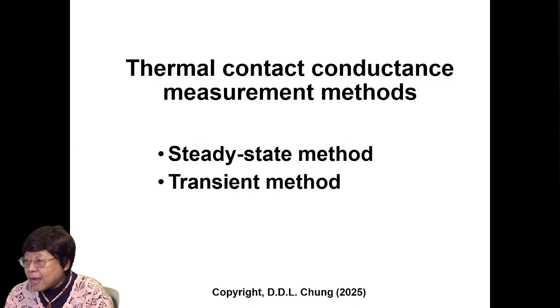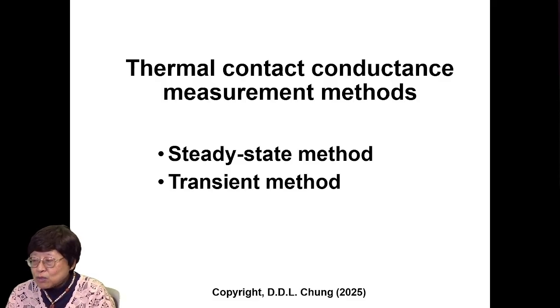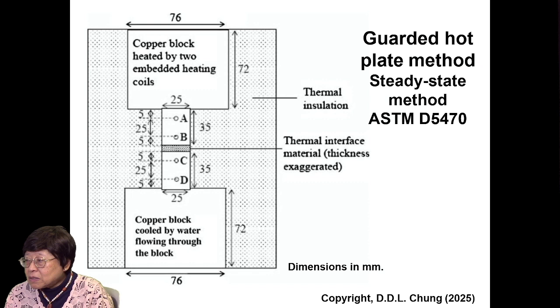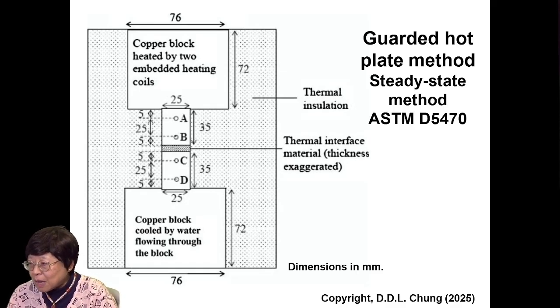For thermal contact conductance measurement, there are two methods, steady-state method and transient method. The guarded hot plate method is the steady-state method, with the heat flux being vertical, and the TIM is sandwiched by two, say, copper blocks, each block having two holes for inserting two thermocouples. So you have A, B, C, D, four points to measure the temperature versus the position in the vertical direction.